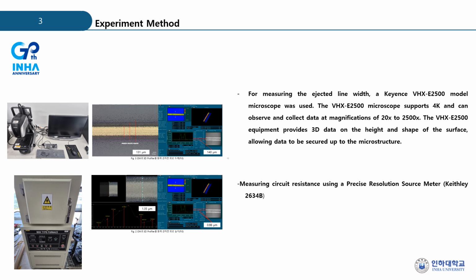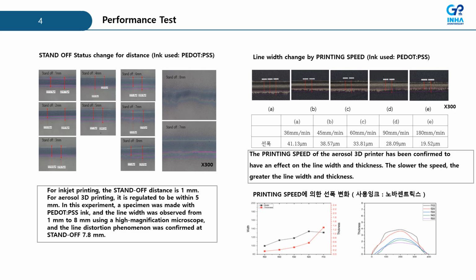The circuit resistance was measured using a precise high resolution source meter, Keithley 2634B. The figure on the left measures the change in line width with respect to the standoff distance. In the case of inkjet printing, the standoff distance is 1 mm. In the case of aerosol 3D printing, it is regulated to be within 5 mm.